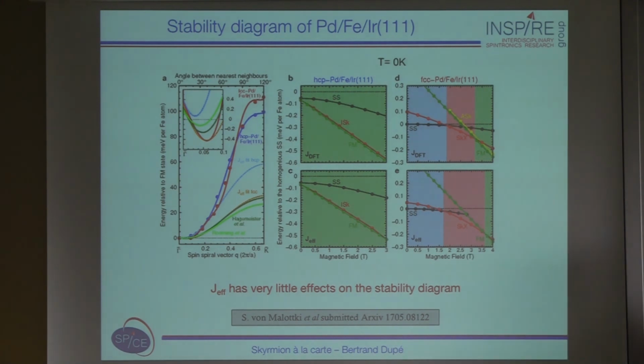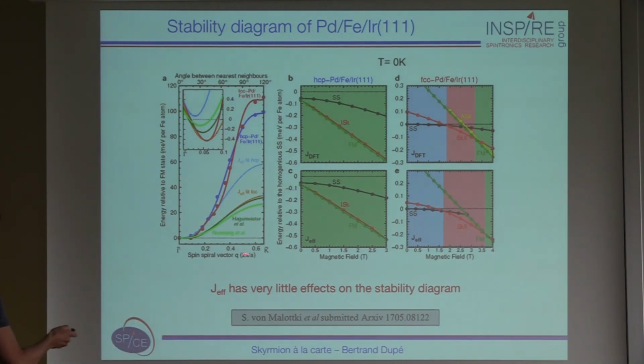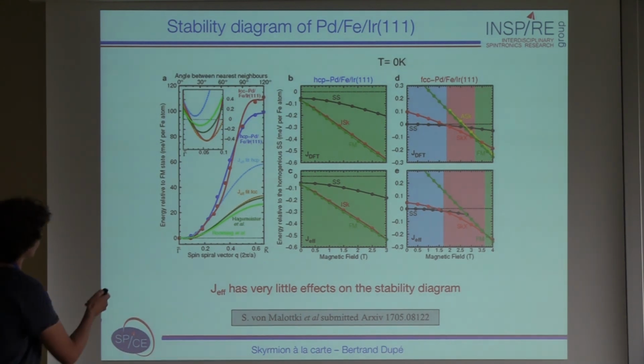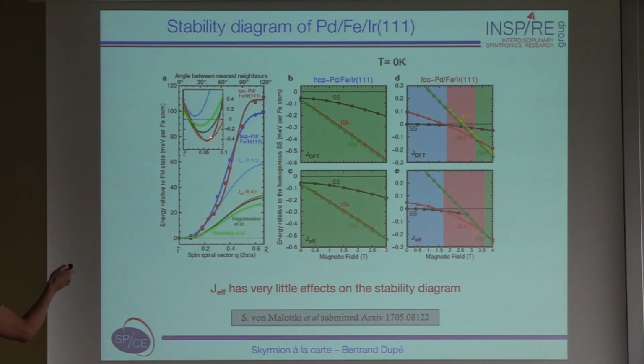Alors, this is a complex graph. There is a lot of information here. So here I show you the energy dispersion curve as a function of the spin spiral for palladium FCC on iron on iridium 111 and palladium HCP on iron on iridium 111. I show you also different ways of modeling the important region of the dispersion curve, namely this minimum here, the minimum of the exchange and the DMI, which characterize actually the period of the spin spiral and which characterize the ground state. So actually, we find different sets of effective J's depending on what we wanted to model.